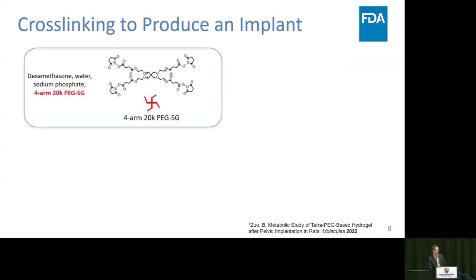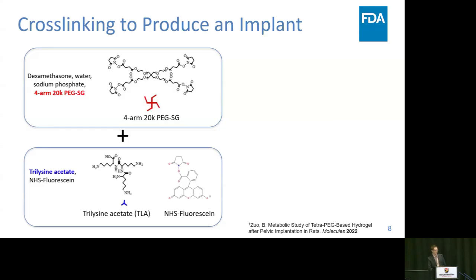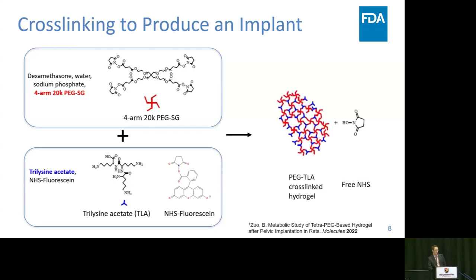So looking at the cross-linking mechanism and manufacturing that's used to produce the implant. This is the chemistry behind it in this particular case. There's a solution that contains dexamethasone, water, and sodium phosphate buffer, as well as the one key functional excipient, which is the 4-arm 20K PEG with succinimidyl glutarate end groups. And this gets combined with the cross-linking reagent, which is trilysine acetate, which contains these terminal amines. And this is also usually conjugated with a dye so that the insert can be visualized. And then this proceeds to a cross-linking reaction where amide bonds are formed, and you have dispersed particles of dexamethasone within this covalently cross-linked hydrogel matrix, and then you end up with the free leaving end groups that pop off the polymers.